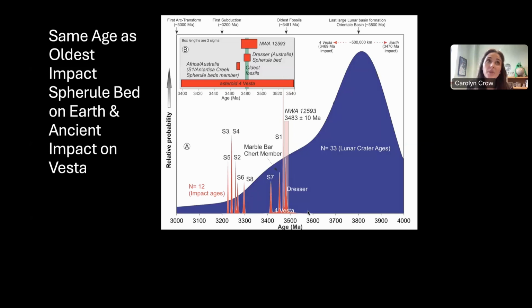It's also an important age because this is the time period where the lunar and the terrestrial impact records kind of diverge. There's a gap, right? In the back here is this blue line. These are crater counting ages for large craters. You can see that they taper off as we're getting closer to 3.5. And this is the oldest thing. So these craters are some of the younger things that we have constraints for in terms of big craters on the moon. And then we have basically the terrestrial record coming in from the left. And so this is really interesting that they are overlapping with each other.